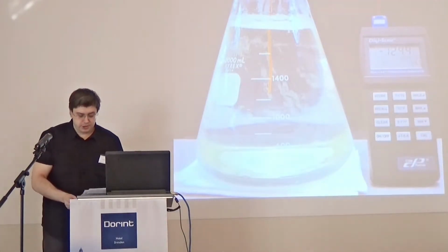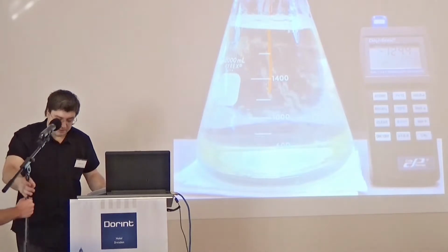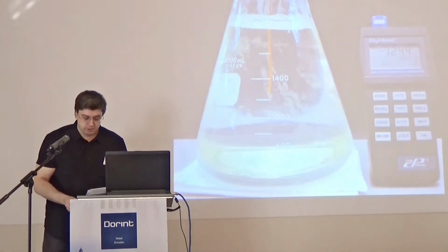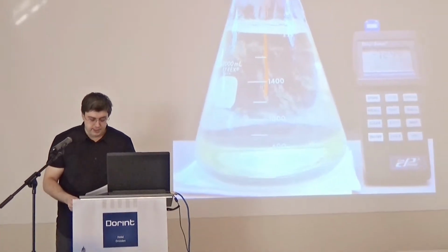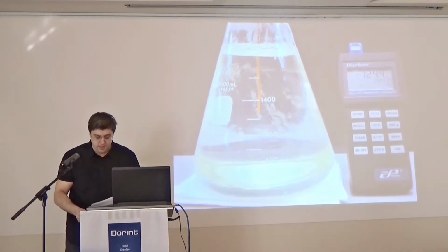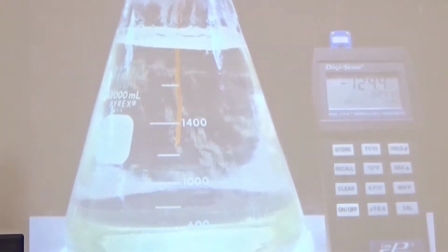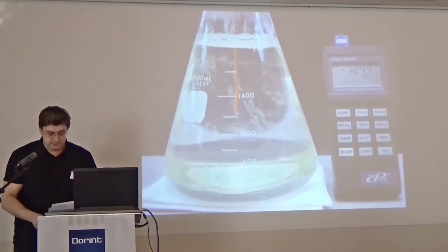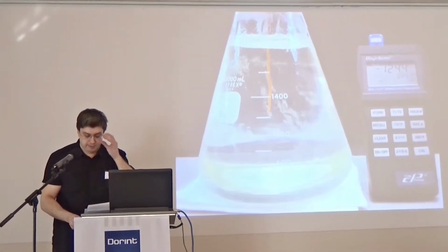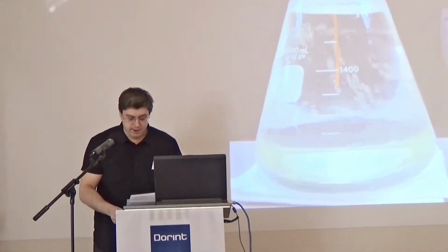The main condition for the onset of vitrification during cooling is an increase of liquid viscosity to about 10 to the 13th Poise. On the molecular level, it is expressed in loss of rotational and translational degrees of freedom, leaving only bond vibration within a fixed molecular structure, which leads to a decrease in the specific heat and thermal expansion coefficient.